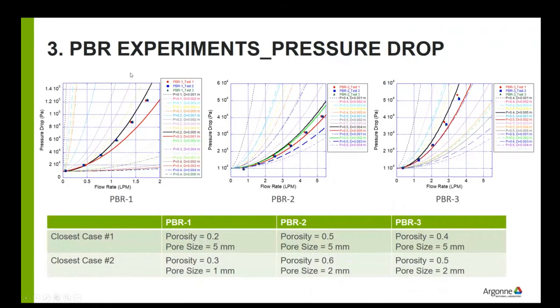And in the PBR experiments, after each experiment, we also measured the pressure drop across the test section to indirectly measure the blockage of each test section. By measuring this pressure drop, we can indirectly estimate the porosity and pore size of the relocated fuel. The PBR1 experiment shows the highest pressure drop values compared to the other pin bundle test sections. PBR2 shows the lowest pressure drop values because it has the largest amount of eutectic formation, so that uranium can be dispersed furthest. And in PBR3, the pressure drop values are in between these two.